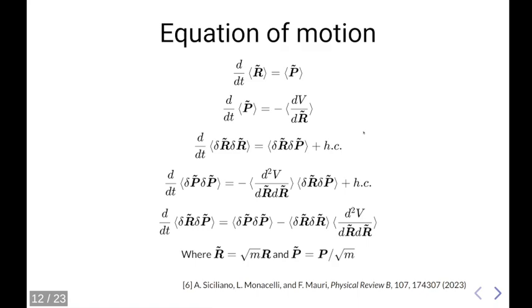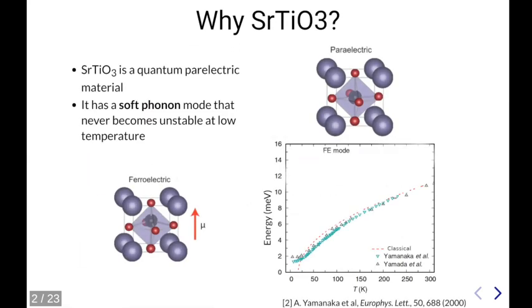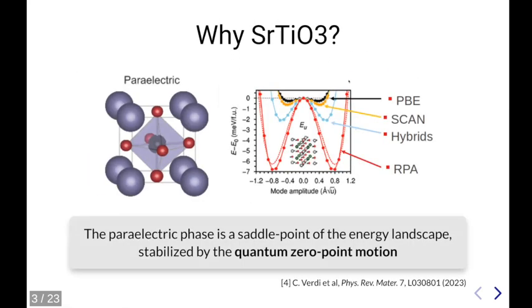At the beginning, the slide that you showed about this paraelectric phase. Yeah, here, no, the previous one, excuse me. Could you repeat the argument here? You have these calculations, and I didn't understand what the message was. So the message is that all density functional theory, no matter if you do GGA, meta-GGA, hybrids, or RPA calculations, all of them give the paraelectric state to be a saddle point, so to be unstable, if you want.